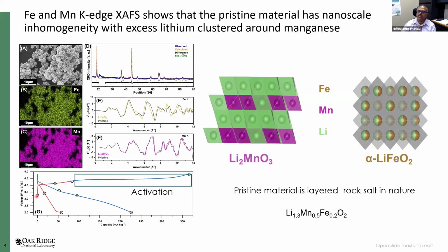So during the first charge, the voltage goes up. This is typically expected to be because of a conventional oxidation of the transition metal. In this case, one would expect it to be iron going from a 3-valent state to a 4-valent state. And then there is a very large plateau, which is a fingerprint of almost all lithium-rich material. This plateau is called the activation plateau, where the material gets activated by a process.